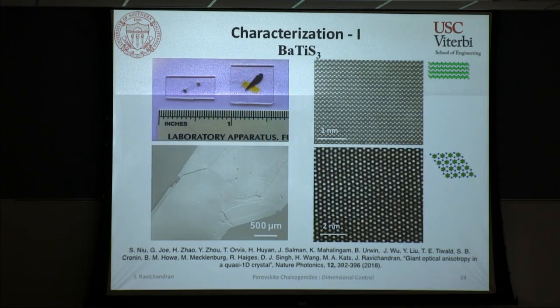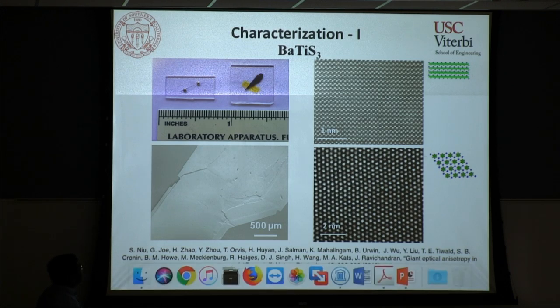So this got us interested in growing crystals of these materials. We picked barium titanium sulfur 3, BaTiS3, and we grew large single crystals using the vapor transport method. It's exactly the same method, though there's no flux in this case. You just have a halogen transport agent, and you can grow large single crystals several millimeters by several millimeters in size. You can see in SEM images that these have very nice crystallographic facets and terminate nicely.